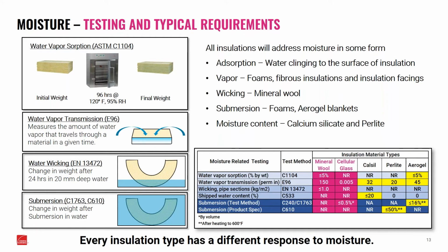Wicking for pipe sections, you'll see that the metric there is it will only absorb 1 kilogram per square meter. If you can imagine, that's essentially 2.2 pounds over roughly a 3 foot by 3 foot section, which isn't a lot of water. Again, not an ASTM requirement, but something you see in industry, and not required of the other insulation types. If you look at shipped water content, interestingly enough, calcium silicate insulation has an ASTM requirement that it can have no more than 20% moisture content as received, or as shipped, I guess. So that's how that addresses moisture.